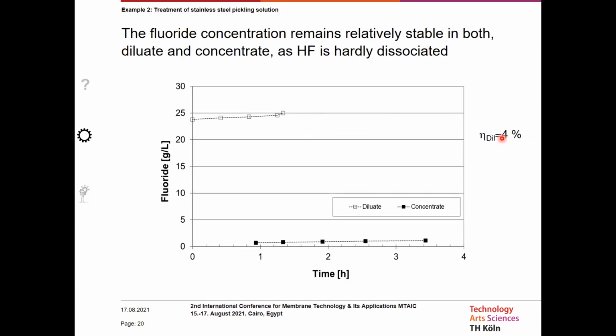But when we look now at the fluoride concentration, fluoride, or the fluoric acid, is a very expensive component. So it would have been nice to recover it as well in the concentrate. But what we can see is that the concentration of the fluoride stays more or less stable in the concentrate and also in the dilute. That means we have hardly any transport of fluoride ions, and this is attributed to the fact that HF is hardly dissociated and therefore cannot be transported in the electric field.